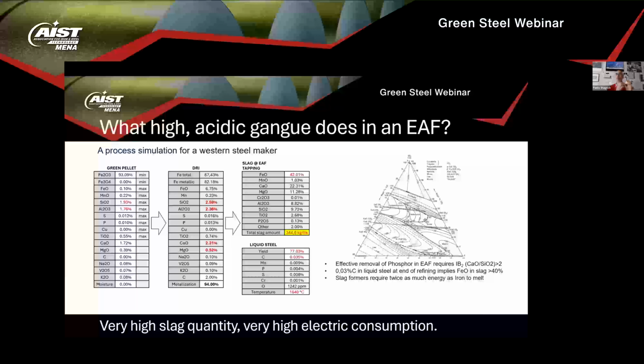And then there is a common misconception that the electrical furnace cannot deal with BF grade material. Of course it can. Electrical furnaces can melt pretty much everything. The real point is if one thinks to charge 100% blast furnace grade pellets, which have high gangue, and acidic gangue at that, into an electrical furnace, closing the process in a way like the one depicted in this graph, which points to the production of flat steel. So you see that in the liquid steel, the carbon content is 0.035, and so on and so forth. Tapping temperature is also consistent with flat steel production. One ends up with a huge quantity of slag. This is by operating the EAF in the normal way, okay?